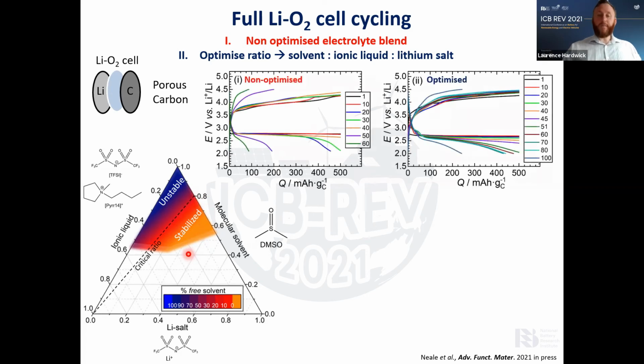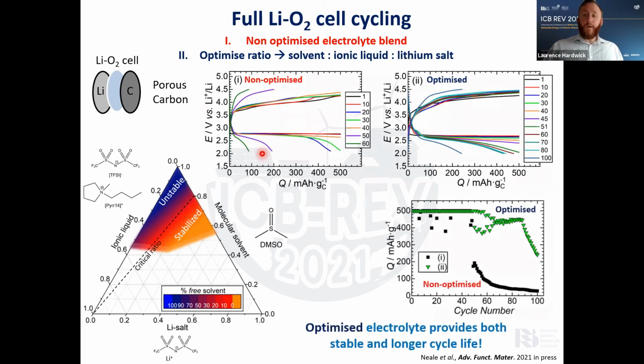And so within our cells, we cycled this, and from our optimized electrolyte, a very unstable solvent can be stabilized by carefully coordinating with lithium within this. We can get much more stable cycling for over 50 cycles, and it still has some cyclable capacity of about 100. We see that when we have a non-optimized ternary blend, the cycling decays and the cell is dead by 60 cycles. So we've optimized the electrolyte to be stable along the cycle life. What we're working on now is to investigate different types of porous air cathode material to try and optimize this system even further.